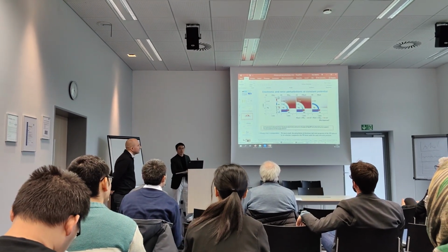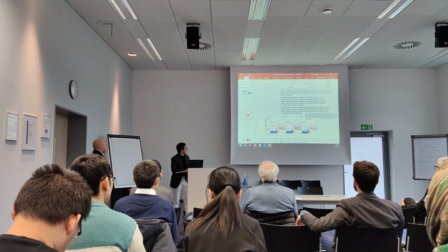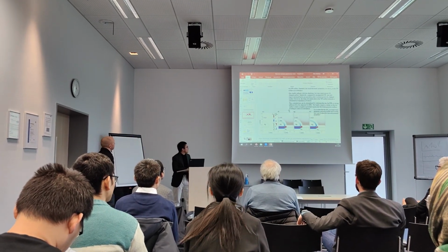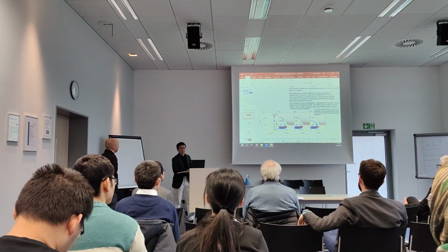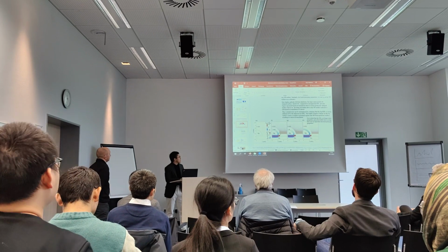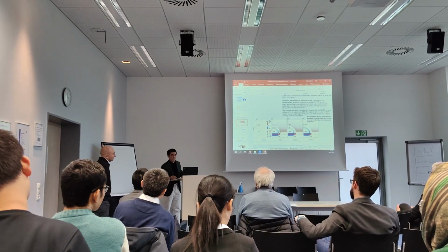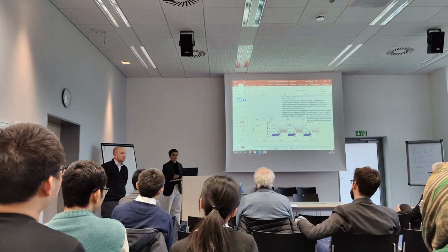It's very dilute, very low ionic strength. And if we go to 100 millimolar, you see the effect is much damped. You see the color is very shallow. So the effect is more pronounced in low ionic strength scenarios.